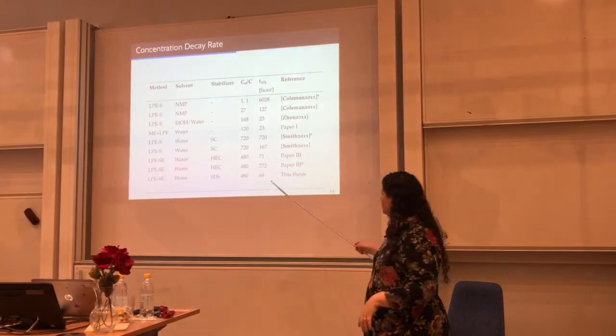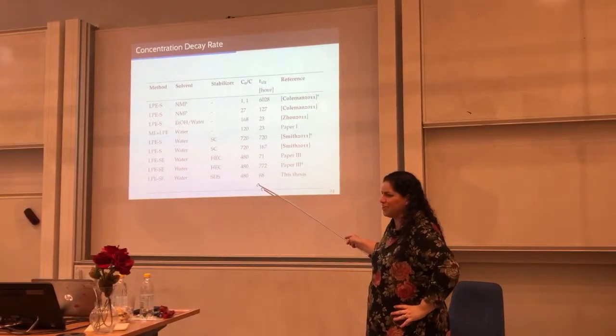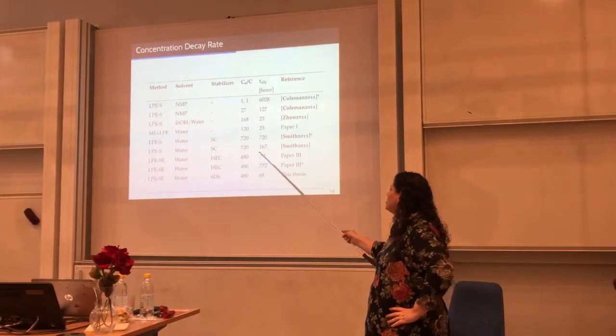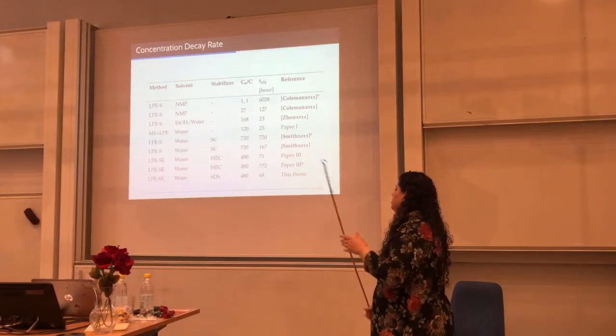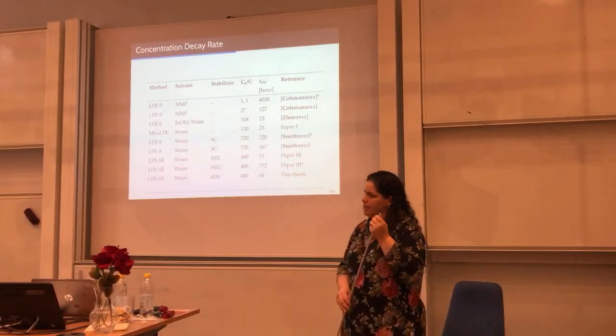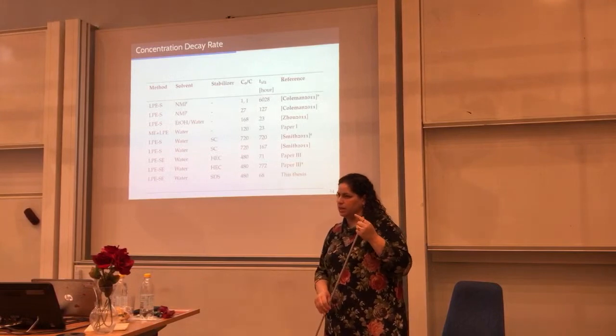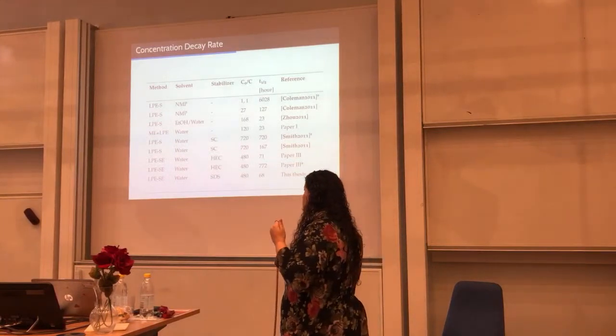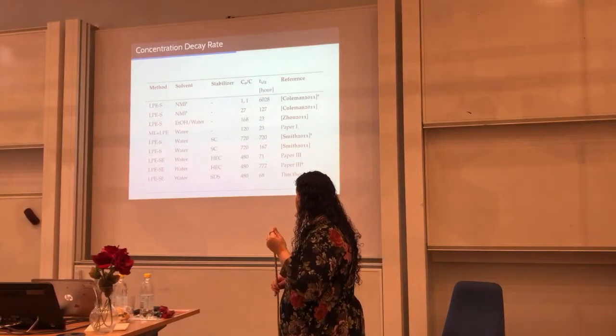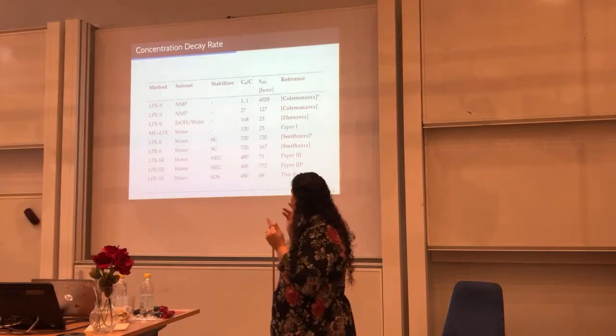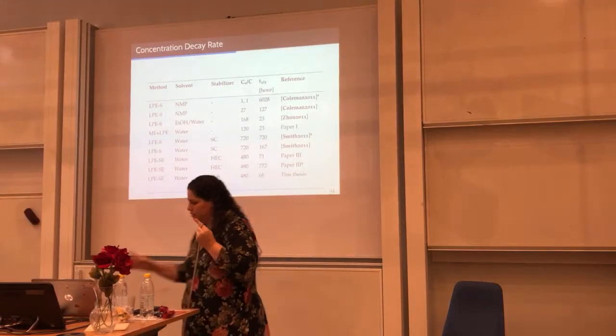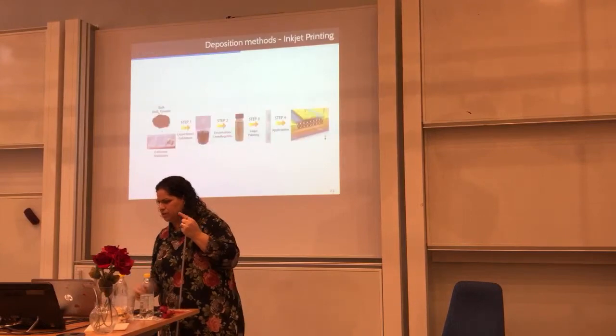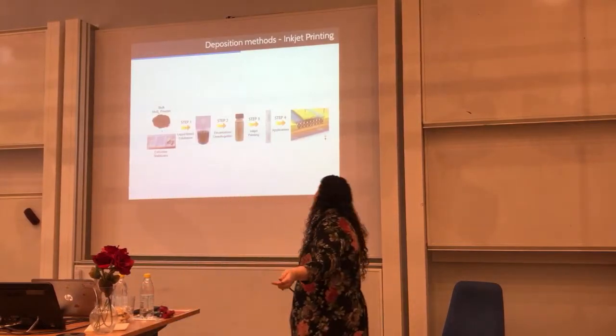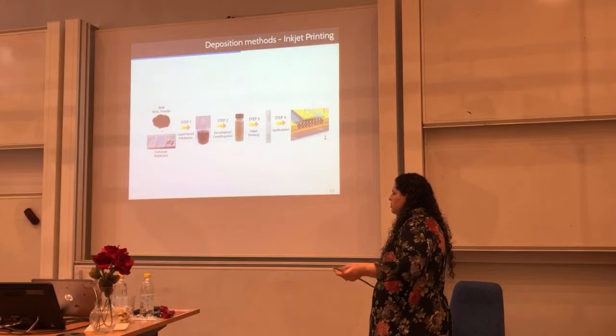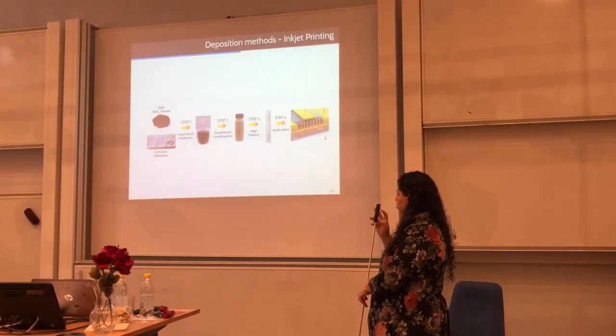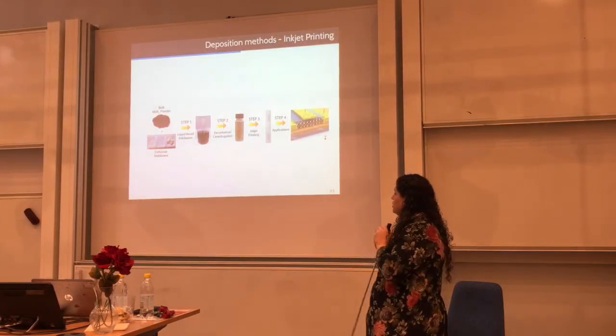My results with sodium dodecyl sulfate were actually worse than his results. Sodium dodecyl sulfate is not one of the best surfactants for liquid phase exfoliation. There are a number of other surfactants that surpass it, but my intention at that time was just to reduce the surface energy to be able to print, not really to work so much on the stability using surfactant or the increase of concentration.